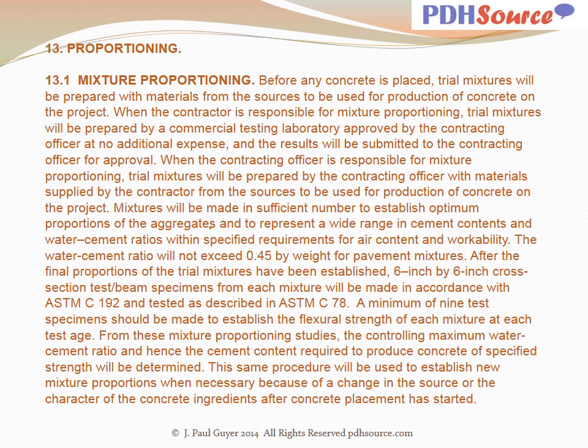After the final proportions of the trial mixtures have been established, 6-inch by 6-inch cross-section test beam specimens from each mixture will be made in accordance with ASTM C192 and tested as described in ASTM C78. A minimum of 9 test specimens should be made to establish the flexural strength of each mixture at each test age. From these mixture proportioning studies, the controlling maximum water-cement ratio and hence the cement content required to produce concrete of specified strength will be determined.